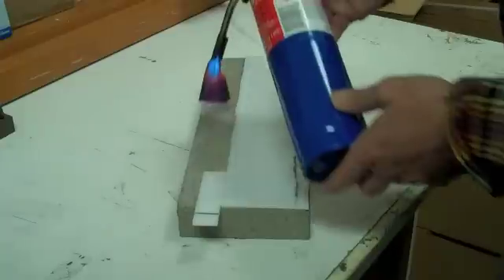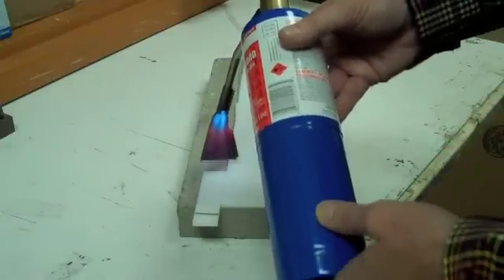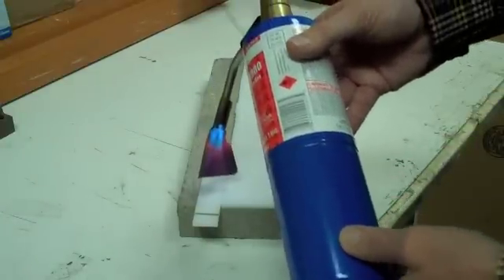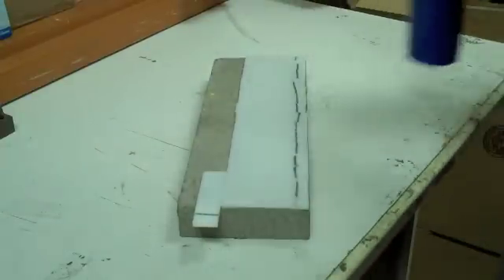The poly should barely warm up. Once this is completed, you'll be ready for bonding poly. The next step is to put water on the poly once again after having the flame treated. If it pools, as it shows in this photograph, it's ready to go.